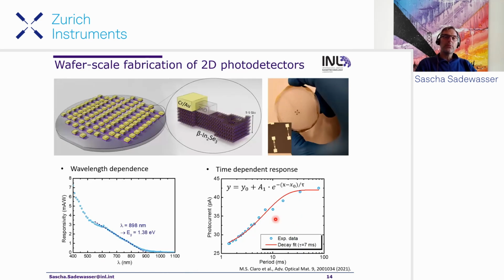So then we use this to make devices. Since we now have the full wafer covered with the indium selenide, we can go to the clean room, use essentially etching, photolithography, and so on, deposit metal contacts, deposit here a protective layer on top, and we fabricate hundreds of these photodetector devices on a single wafer. And this is how it looks in the end. The wafer is full of different devices here, different sizes, and this is a light microscopy image of a single device here. In the middle, you can see the channel.